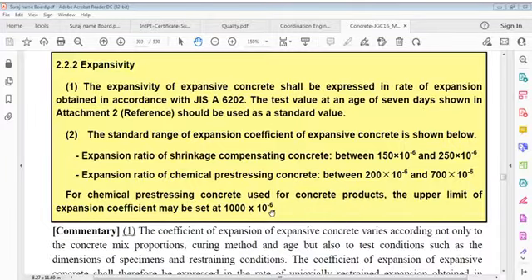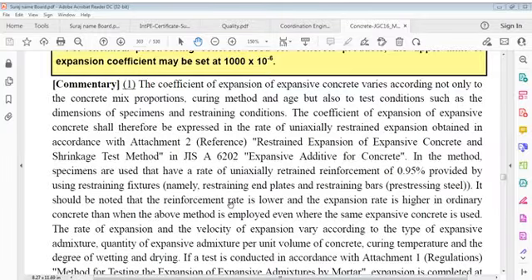For chemical pre-stressing concrete used for concrete products, the upper limit of expansion coefficient may be set at 1000 x 10^-6. Coefficient of expansion of expansive concrete varies not only according to concrete mix proportions, curing methods and age, but also to test conditions such as dimensions of specimen and restraining condition. Coefficient of expansion of expansive concrete shall therefore be expressed in rate of uniaxially restrained expansion.